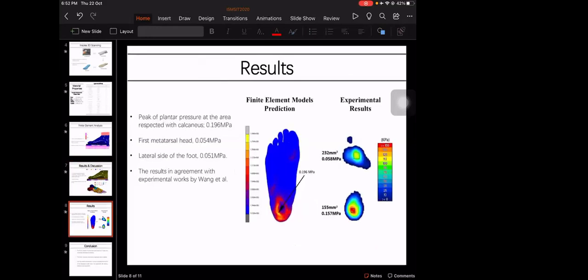So here is the finite element model prediction, and on the right side are the experimental results that we referred to. As you can see in the slide, the peak plantar pressure at the area of the calcaneus recorded 0.196 megapascal. Looking at the experimental results, the peak was 0.157 megapascal. And high pressure was also recorded at the forefoot area. In our study, we recorded 0.054 megapascal at the first metatarsal head, and on the lateral side of the foot 0.051 megapascal.